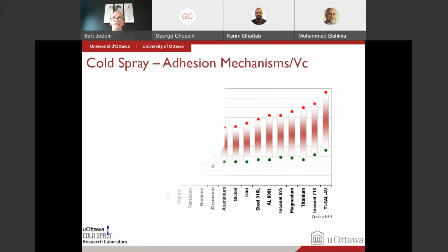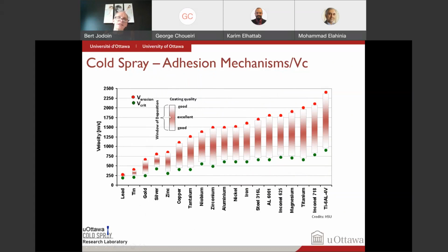For each material, you have different critical velocities. So here you have kind of a mapping for different materials. Let's say you go with gold. If you want to throw gold particles, you need to throw them at 250 meters per second to start to stick. And if you throw them faster than 600, they're going to start grit blasting. You have this for a bunch of materials that we've sprayed. The toughest one is the Ti-64, where you need to throw the particles at least at 750 meters per second, but not higher than 2250 meters per second, because you're going to start to basically grit blast.